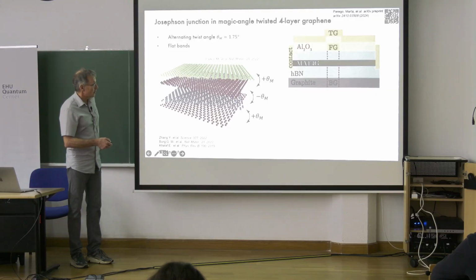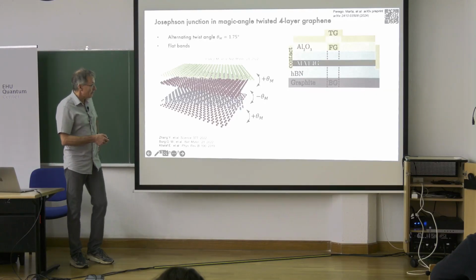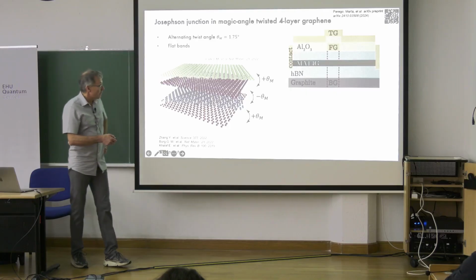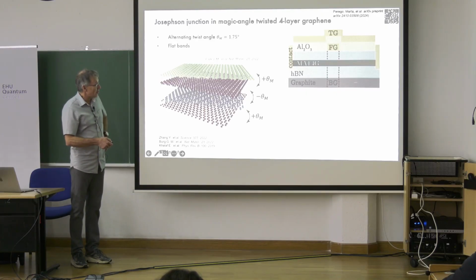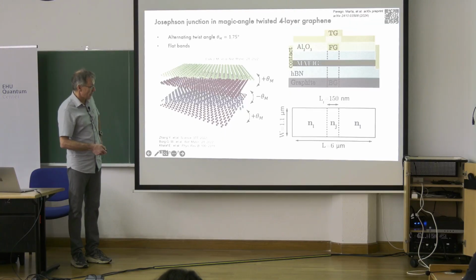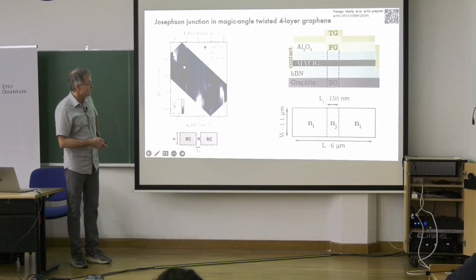It's encapsulated in boron nitride substrate, and you apply gates, bottom gates, top gates, and finger gates with which you produce the junction. So that's the geometry. Its length is like 6 micron. Here it's about 1 micron. And here, by gates, by applied voltage, you make the junction.